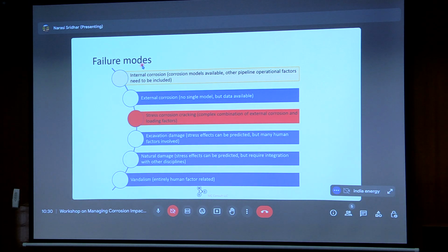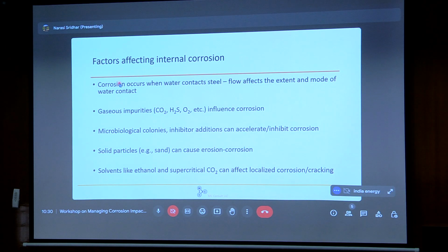So I'm going to show two examples of internal corrosion in SCC, and I'm going to go through it pretty fast in the interest of time. So internal corrosion occurs because whenever water contacts steel, you have potential for corrosion, but water alone doesn't cause corrosion. You need impurities in the natural gas in the form of CO2 and H2S and oxygen that influence the corrosion. And you also have microbiological colonies. And of course, you can inhibit corrosion by adding organic inhibitors. And of course, sometimes you get sand from production, so you get these solid particles that cause erosion. And then if you add solvents like ethanol or supercritical CO2, they can affect localized corrosion as well because they solubilize other species. So there is a bunch of factors that affect internal corrosion.